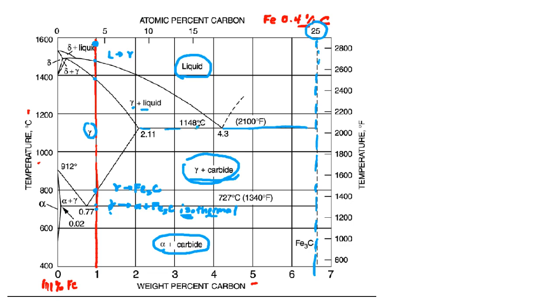And this particular reaction you'll notice involves, where these involve two phases - liquid going to gamma, gamma going to Fe3C - this one involves three phases: gamma going to alpha plus Fe3C. And that is one of the reasons why it takes place all at one temperature. Now there are other, as I mentioned, horizontal transformations here on this graph. And you'll kind of recognize them by this characteristic shape. There's a horizontal line and then you see this valley going into this line. You've got the same thing going on here. There's a valley going into this line. I can extend it across here. And as I said, there's another transformation like this. It's actually not the exact same one, but you'll see something characteristic: a horizontal line and some sort of valley, whether it's above or below. And what that's telling us is it's telling us the transformation involves all of the single phase regions that the transformation touches as a boundary.